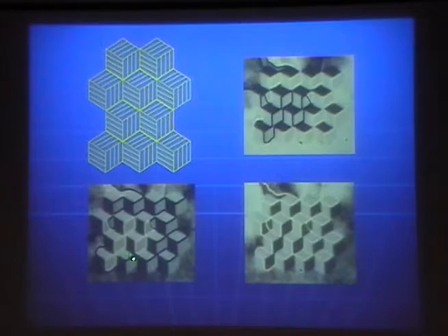We have a completely dark boundary here, and we have a bright boundary, and we have a neutral boundary. So there are 3 different boundary contrasts. And those different contrasts correspond to different orientations or different connections between these domains. So the transition again involves symmetry switching.